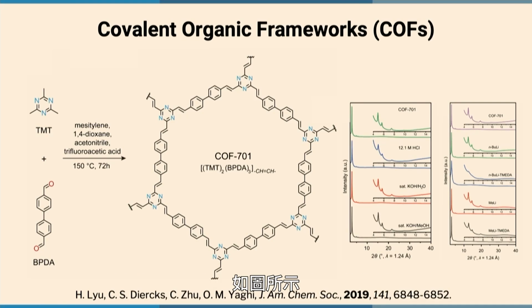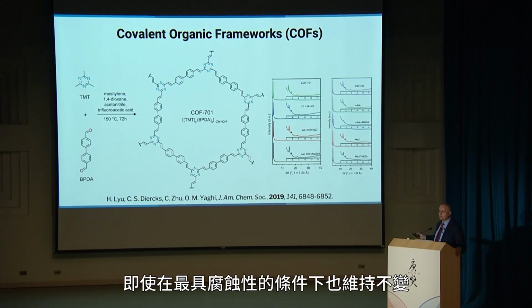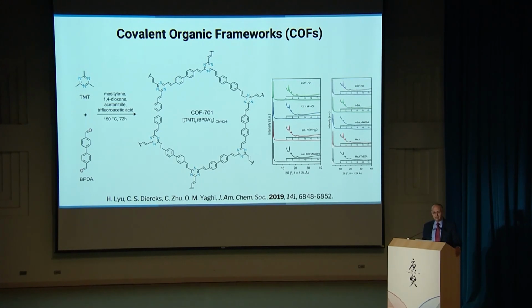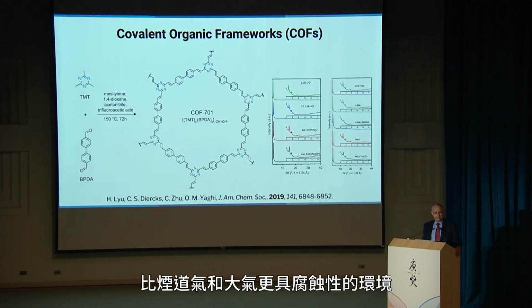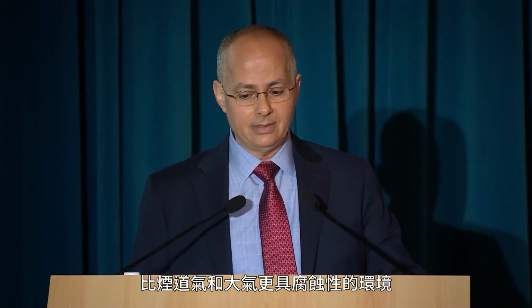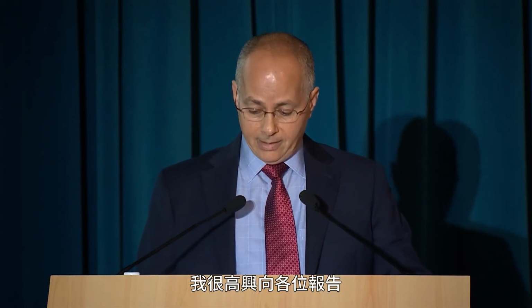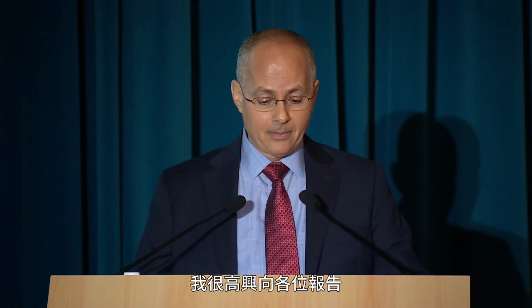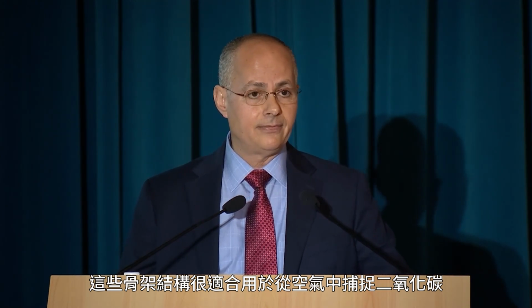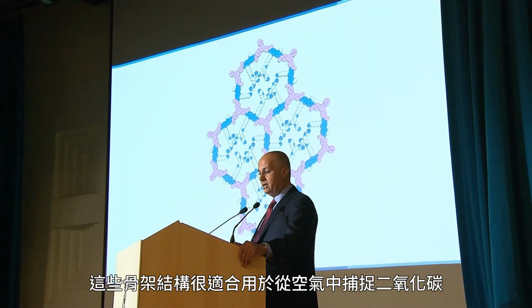And that's shown here. This in itself is a major development in chemistry. And you can see the stability of the material is unchanged even under the most corrosive conditions, much more corrosive than flue gas or the atmosphere. So I'm very happy to report that, in fact, these frameworks are ideal for capturing CO2 from air.